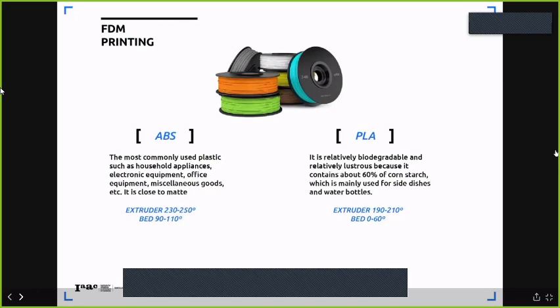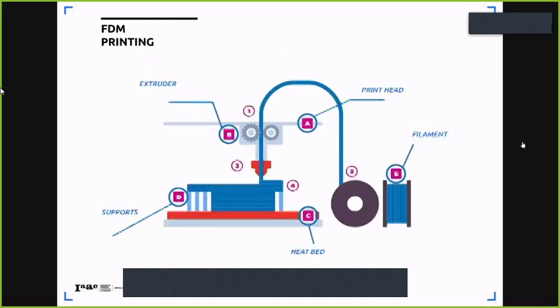It means PLA at 60 degrees starts becoming malleable. It means you can compress it a little bit. It's like a little bit of Play-Doh. Not exactly Play-Doh, but kind of a Play-Doh texture. That is the temperature that you always want the print bed set to, to help the bonding of the model on top of the bed so it doesn't move.